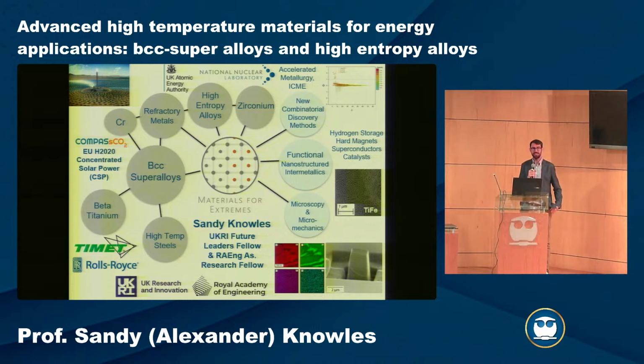The challenge at the moment is that most of those are really based off CALPHAD. So it works really well for nickel alloys and for steels, but if you go into an unusual alloy like a chromium alloy or a vanadium alloy, if we haven't looked at the phase diagrams, we just don't have the data. So there is an idea that we can AI or machine learning our way out of the problem, but the challenge is just that we don't have the data.